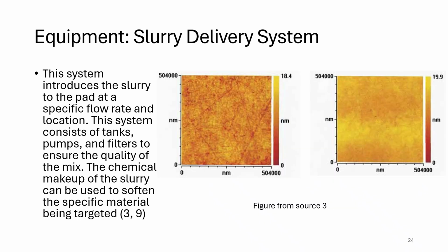Slurry filtration is a critical part of the slurry delivery process. The graph on the left is a copper surface that was polished with an unfiltered slurry. The graph on the right is a different copper surface that was polished with a filtered slurry. The results from the filtered slurry mixture are significantly better than the unfiltered slurry, with a noticeably lower defect rate.